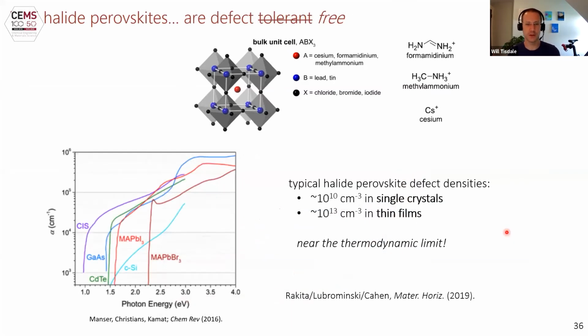And for a long time, we thought that what was special about these materials is that they're defect tolerant. The emerging understanding, and this is a school of thought that is highly debated, but one that I subscribe to, is that these materials are not defect tolerant, that they are actually largely defect free. If you do measure the absorption coefficient as a function of photon energy, for the perovskites, you can see very, very sharp onsets in the optical absorption, which indicates that there's a very low density of defect states extending into the band gap. Estimates of defect densities in perovskite single crystals are order 10 to the 10th per cubic centimeter